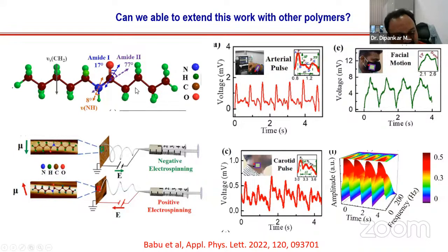Okay, so odd nylons are piezoelectric in nature, and through the electrospinning technique, what we did here is apply a positive bias. Okay, and this is the grounding one. You can use a metallic drum, etc. But if we change to a negative potential on the needle bias, then you have a different type of surface potential of the fiber. That is the interesting part we have recently published in APL: simply by changing the bias in the electrospinning technique, we can rotate the molecule. You see, the oxygen is on this side, but here it is on the other. So you can change the direction of the polarization. That's what we prove in this work.